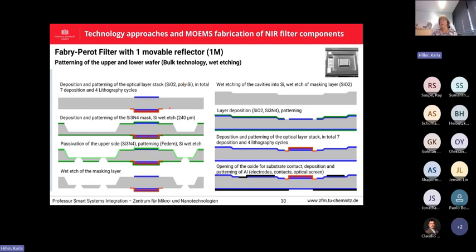And using lithography and etching, we remove most of the layers so that they stay only in the area of the optical aperture. Then we have used a silicon nitride mask to cover the surface during the wet etching in KOH solution. So we pattern this from the backside. We have different membrane thicknesses, around 50 to 70 micrometer, depending on the design. So we etch until we have adjusted this thickness here. Then we also protect the backside from further etching. And this last etching to get the movable structure can be either wet etching or dry etching.